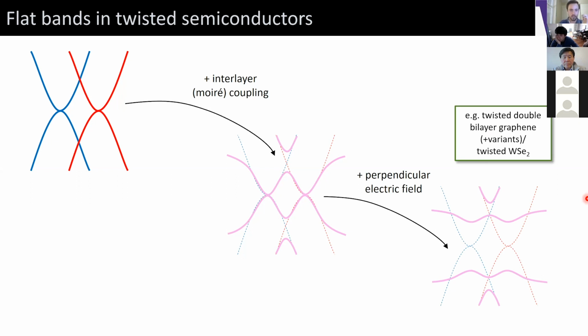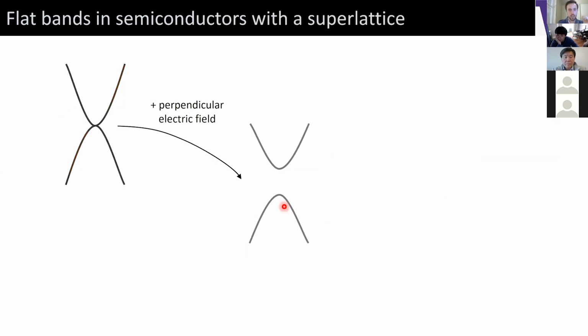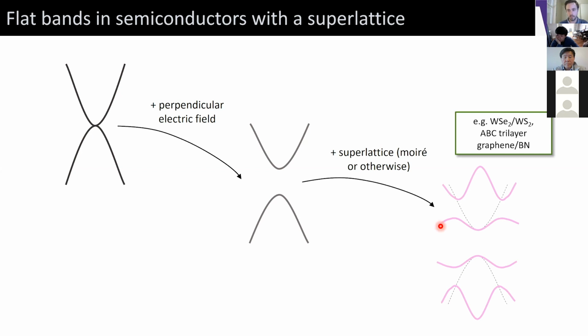We can be more general than this even. We can just take a standard semiconductor that already has a somewhat large effective mass and impose some sort of superlattice potential on it, be it from a Moiré pattern or probably even otherwise. This also gives us a similar path towards realizing flat electronic bands. This Moiré pattern will create these low energy Bloch bands. We have an energy gap, which can often be tunable at the neutrality point. And this again gives us some general path towards realizing flat dispersion with correlated states. So this is relevant in systems like rhombohedrally stacked, or ABC, trilayer graphene aligned with boron nitride to get a Moiré pattern, and also WSe2 heterostructures.